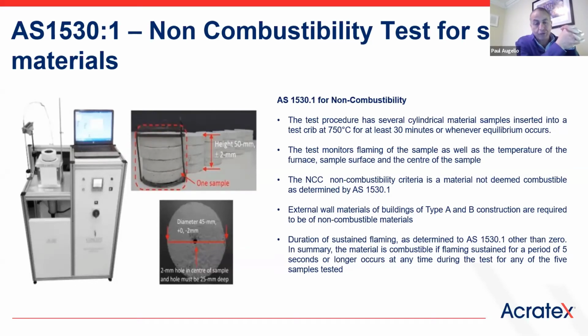And to be able to do that, you've got to have 6 specimens that are all formed, 50 millimetre high, about a 40 millimetre diameter in circumference. And basically, those get dropped into the burner, and basically for 30 minutes. As soon as any flame ignitability comes in within a certain part of that test, it's basically deemed as a fail. So it's really, really severe test to actually pass.